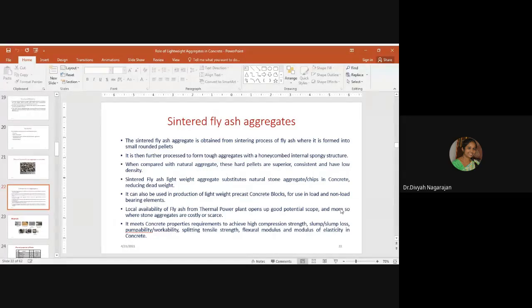The sintered fly ash aggregate is obtained from the sintering process of fly ash, where it is formed into small round pellets. It is then further processed to form tough aggregates with a honeycombed internal spongy structure. When compared with natural aggregates, these hard pellets are superior, consistent, and have low density. The sintered fly ash lightweight aggregates substitute natural stone aggregate or chips in concrete, and hence reduce the dead weight of the structure. It can also be used in production of lightweight precast concrete blocks for use in load and non-load bearing elements.